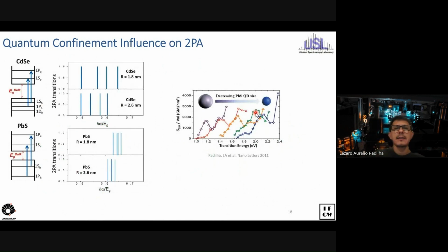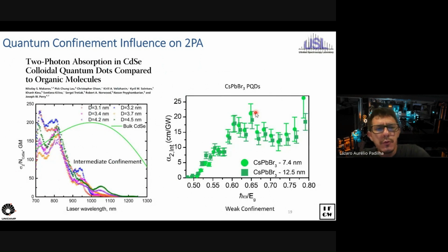But going back to cadmium selenide or perovskite quantum dots, something interesting to point out is this nice work from Makarov et al. and colleagues from 2014, if I'm not mistaken, where they studied a series of different sizes of cadmium selenide quantum dots. What they see is that if they normalize the two-photon absorption cross-section by the number of atoms or number of molecules of cadmium selenide, what they realize is that, especially when you go to the quasi-continuum region here, they're not different from the bulk.